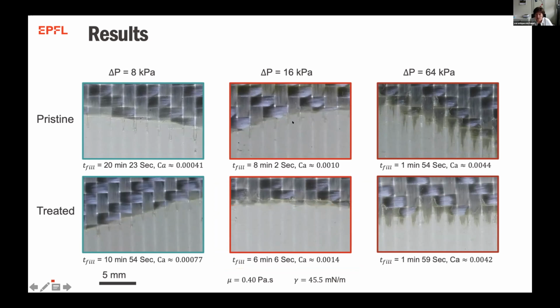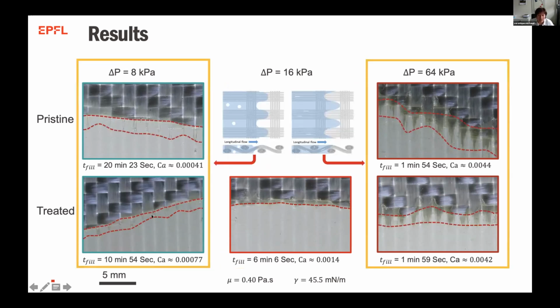So then if I look at the other guys, clearly here I'm going very slowly, and I'm in this case where I have some porosity clearly present in between the tows of the fabric, and some kind of unsaturated zone that I can measure here. And then if I go too fast, I see that I'm just leading flow in between, with these guys here that are still dry. And then I can also measure the length of this unsaturated zone and look at the different things. Of course, here the time to fill is 1 versus 20 minutes. So you see a bit why sometimes we are ready to accept these things.